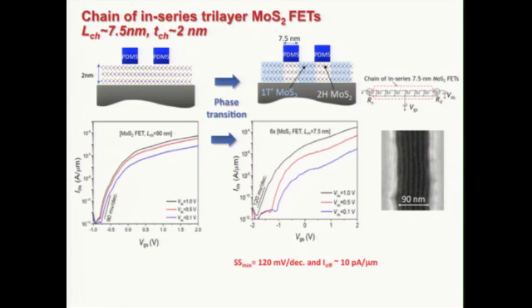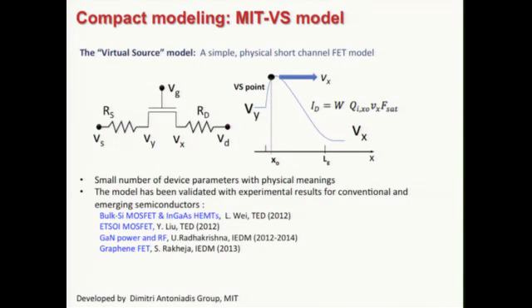As you can see, we still have very low off current, about 10 picoampere per micrometer, and relatively high on current, about a few 100 microamperes per micrometer. So it's already an order of magnitude higher than what we had in our graphene contacted MoS2. And the subthreshold slope is about 120 millivolt per decade, which is an excellent subthreshold slope for such a highly scaled channel.